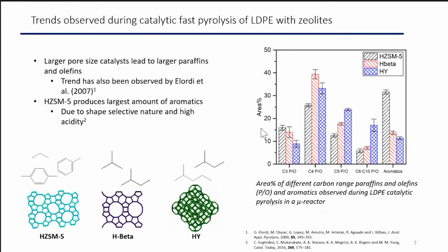So then moving on to the next type of experiments, we are able to see what products form during our pyrolysis. And we are able to see that which catalyst we use changes the relative amount of the products which are formed. So here we have our GCMS area percent of our various products. And we see for LDPE, the main products which are formed are the C3 to C10 paraffins and olefins. We see that the zeolite Y catalyst, which has a larger pore size, results in forming the larger paraffins and olefins in the C5 to C10 range.